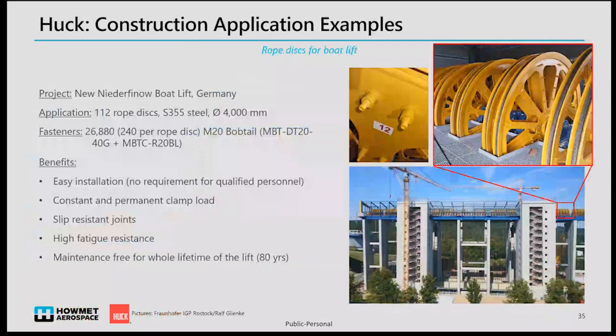And due to the long service life of the structure, which is 80 years, the requirement was to have, basically, a maintenance-free joint. So nobody wanted to remove or retighten or maintain these joints. So we supplied a total of nearly 27,000 fasteners, 240 per disc. And these were installed into the structure and are now in service, and hopefully will also be for the next 70 years in service without any complaints.